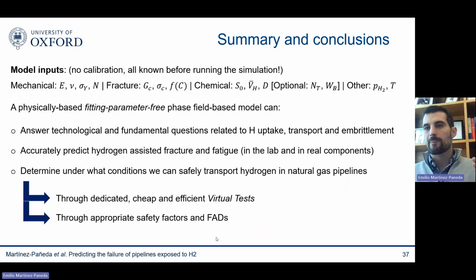And we have shown that the approach that industry is taking is very dangerous because they are focusing on the most common scenario, but one has to design based on the worst-case scenario, which is accounting for this heterogeneous distribution of the welds. And this is critical. Until we find a way of characterizing those heat-affected zones that we know are harder, more brittle, and much more susceptible to hydrogen embrittlement, we don't have a valid tool. So these tools can overcome this gap. These tools can help you quantify what is your safety factor in those problems.